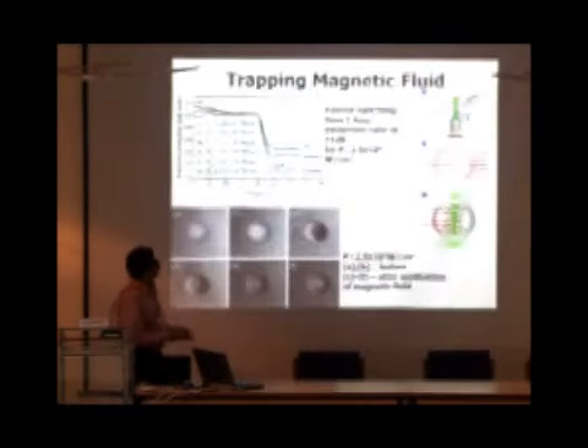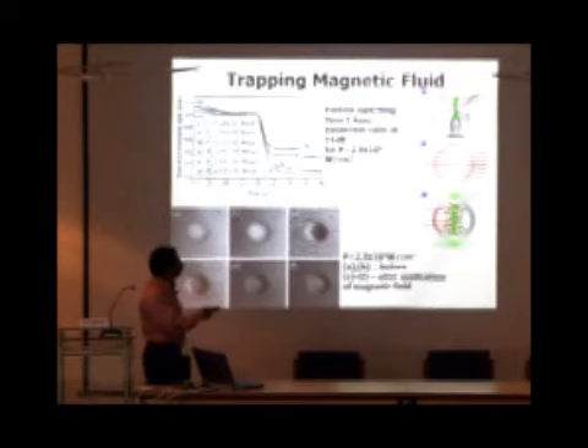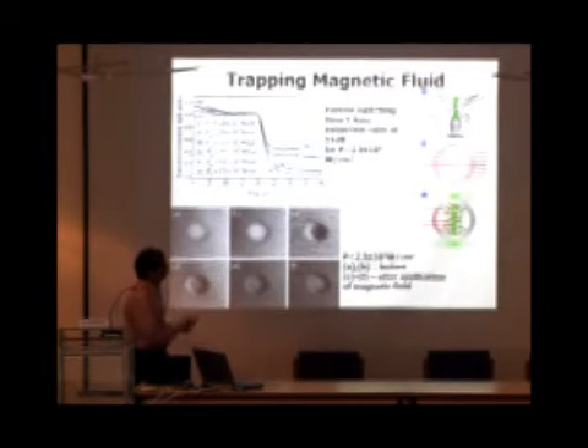Here the process is different, because you have nanometer size particles. Initially the light gets transmitted without any scattering. But as you increase the cluster size by controlling the external magnetic field and your trap light intensity, you're changing the cluster size, and you can see Anderson localization kind of effects in these systems.